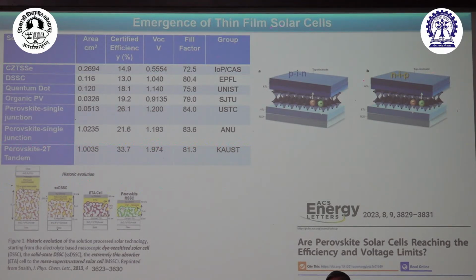There is a Shockley-Queisser limit. It says the maximum you can get on a single junction solar cell is 33%. That is because of your band gap and the light absorption properties. Everything is less, so it's very difficult to get 33. If you take silicon, it's about 28% maximum in the lab. So again, people have been trying to do this with perovskite. They have gotten up to, for single junction, this should be 26.1%, not 21.6. Okay, here it is, 26.1% for single junction.